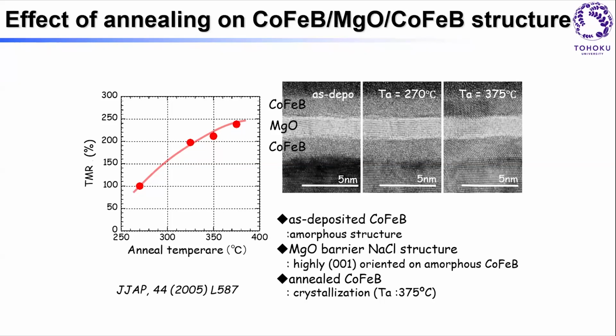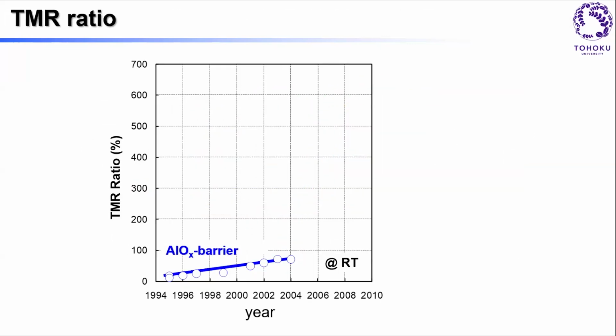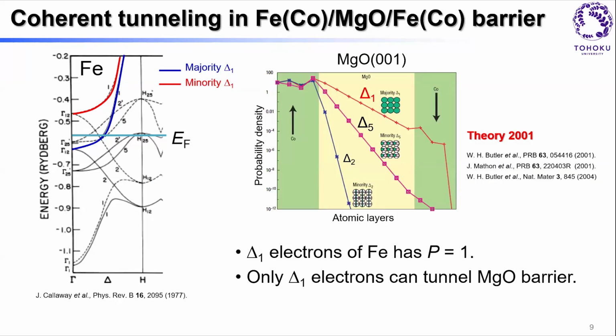we have this cobalt iron plus boron. Adding boron makes the alloy amorphous, and amorphous gives you a very flat surface, and nobody has clearly understood or explained this, but when you deposit MgO on this amorphous material, it organizes itself in a highly 001 oriented structure, and then on top of this, we deposit amorphous cobalt iron boron again and anneal it. And there will be a solid phase epitaxy starting from the interface, and the resulting structure is exactly what we wanted to have here. 001 all the way, and we get a very large resistance change.